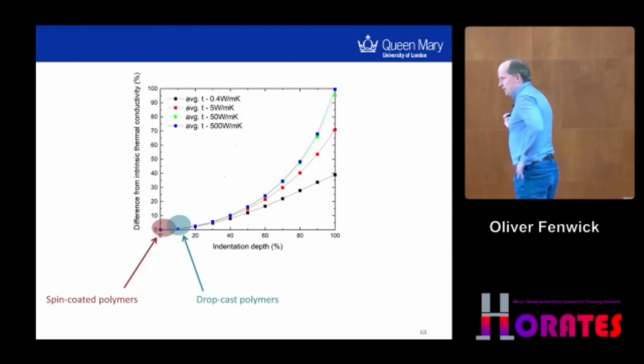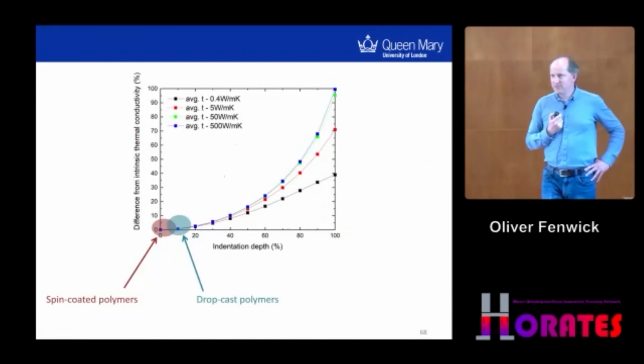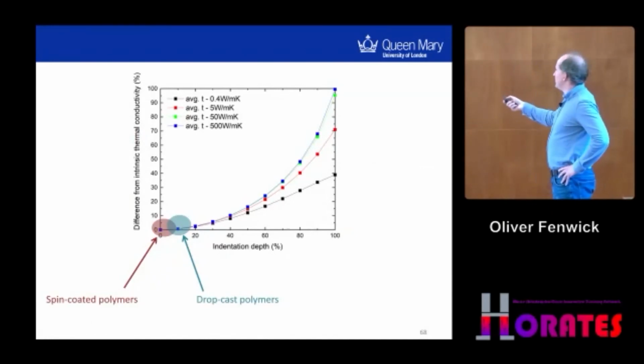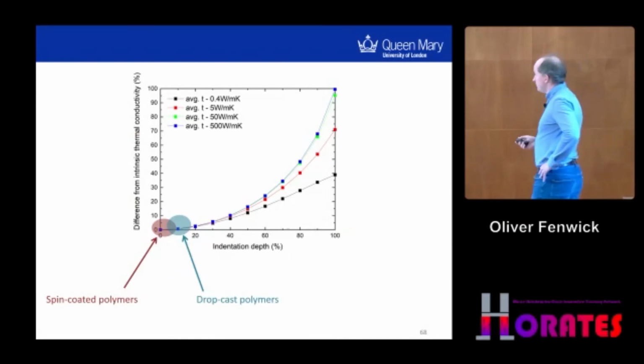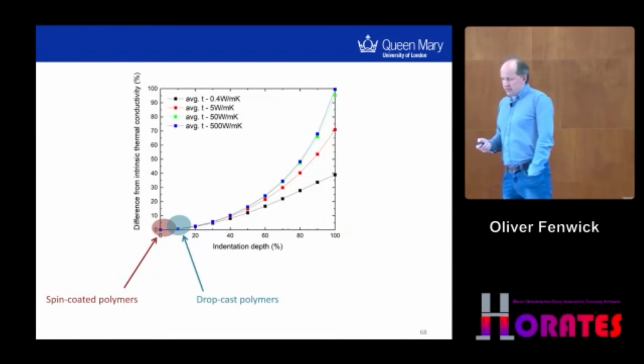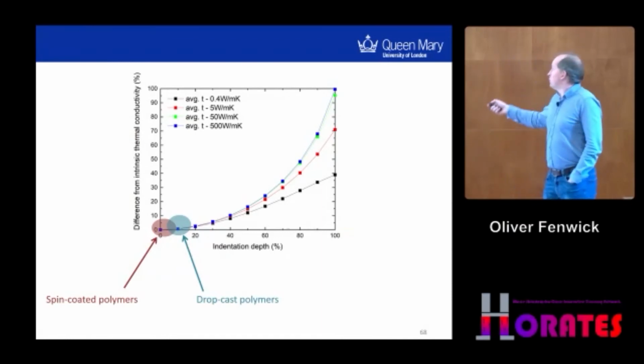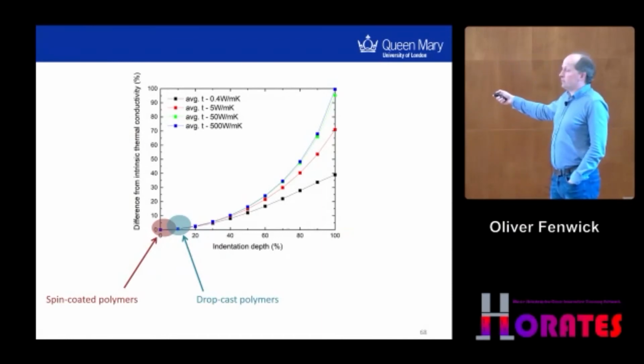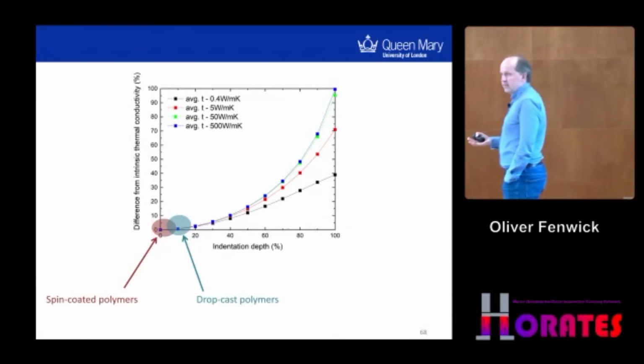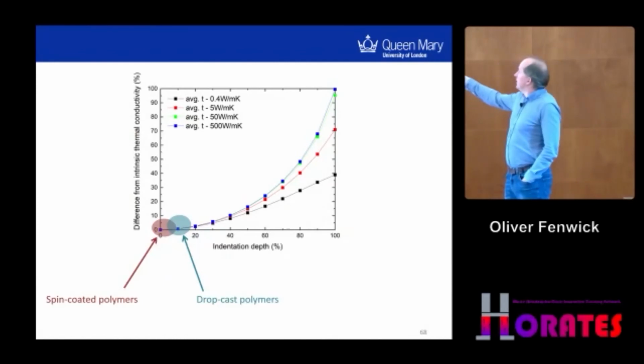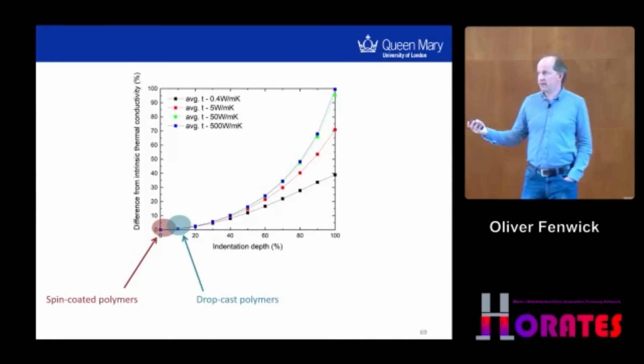The student took a very negative, very pessimistic view of how deep this indentation should go. So 100% indentation is a full break in the film. If we look at what we might actually have on the chip, if we spin coat a polymer film, a single component polymer will be very flat. So we may only expect deviations of less than 10% in the thickness. And we get very small differences from the intrinsic thermal conductivity, which is why we can actually measure it.